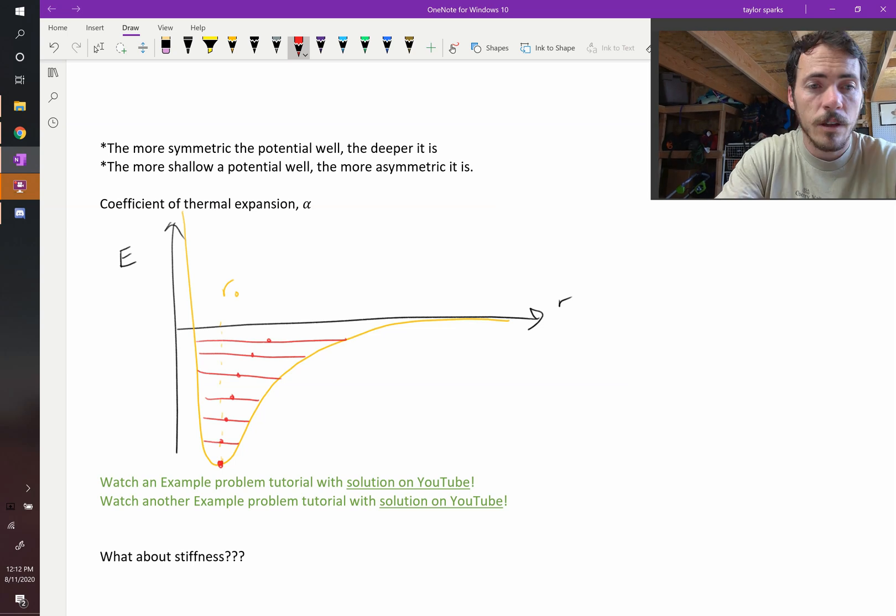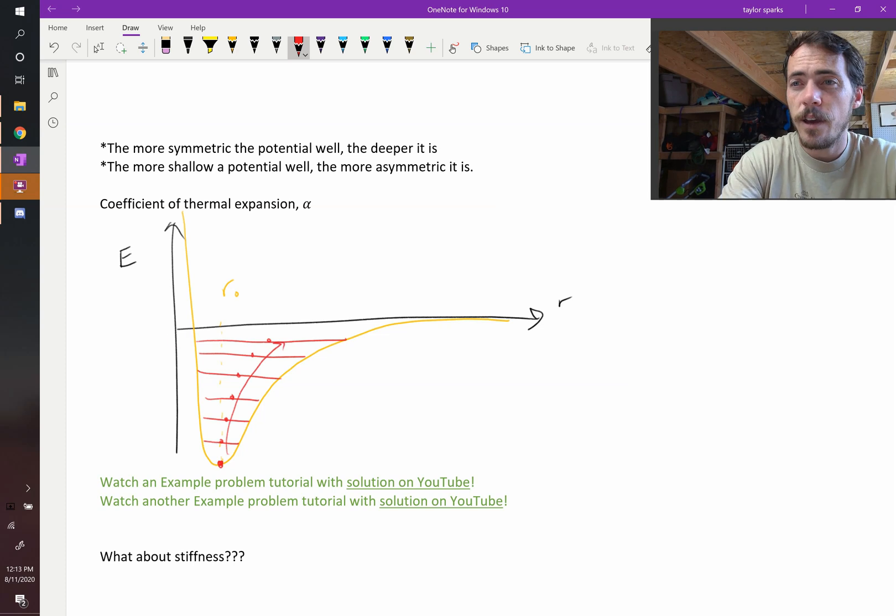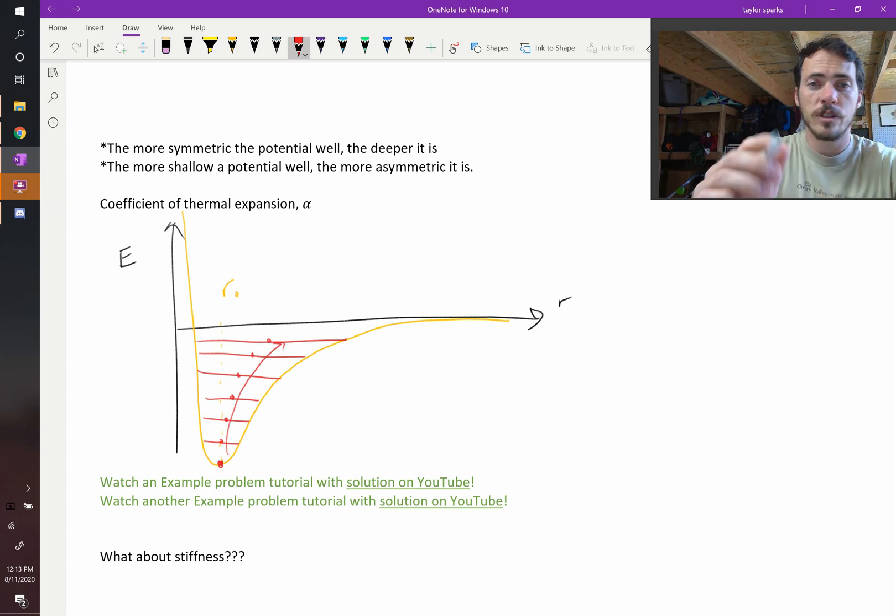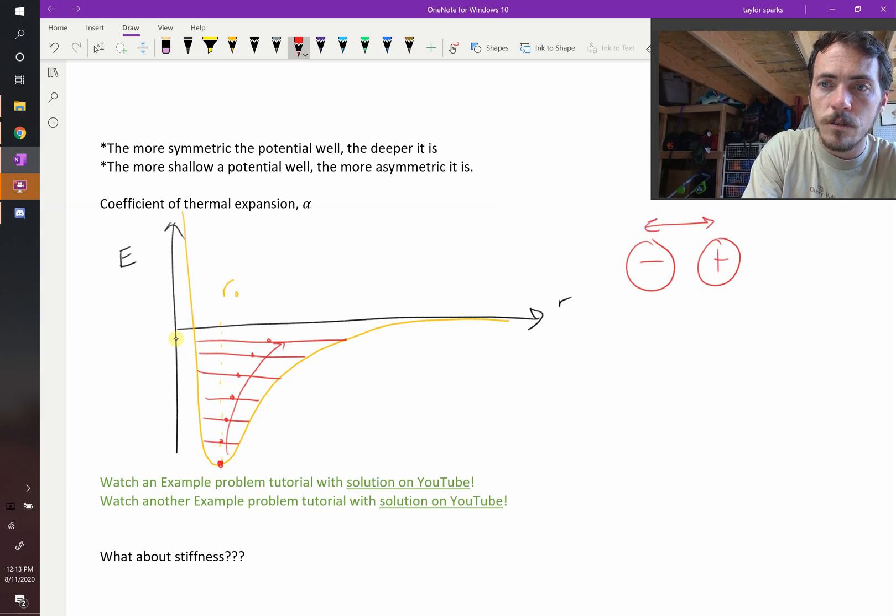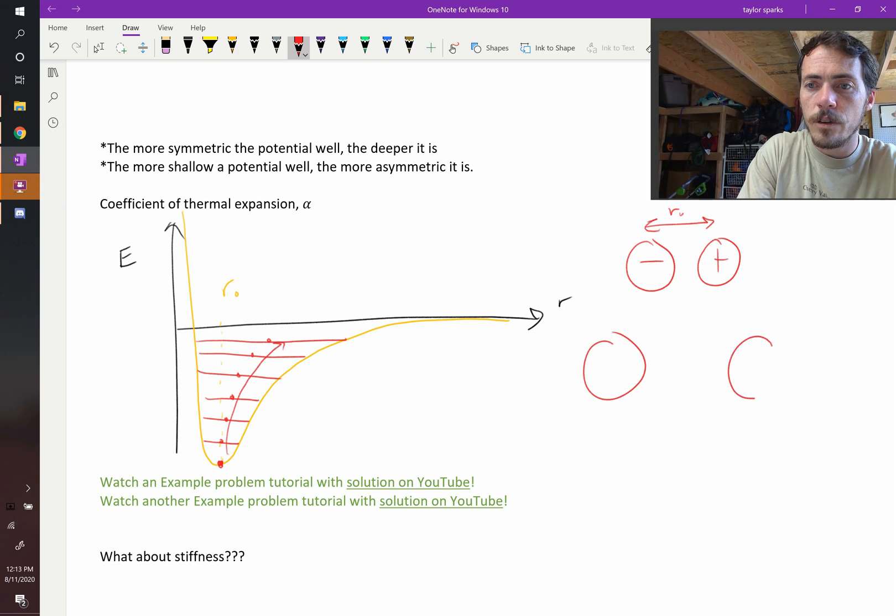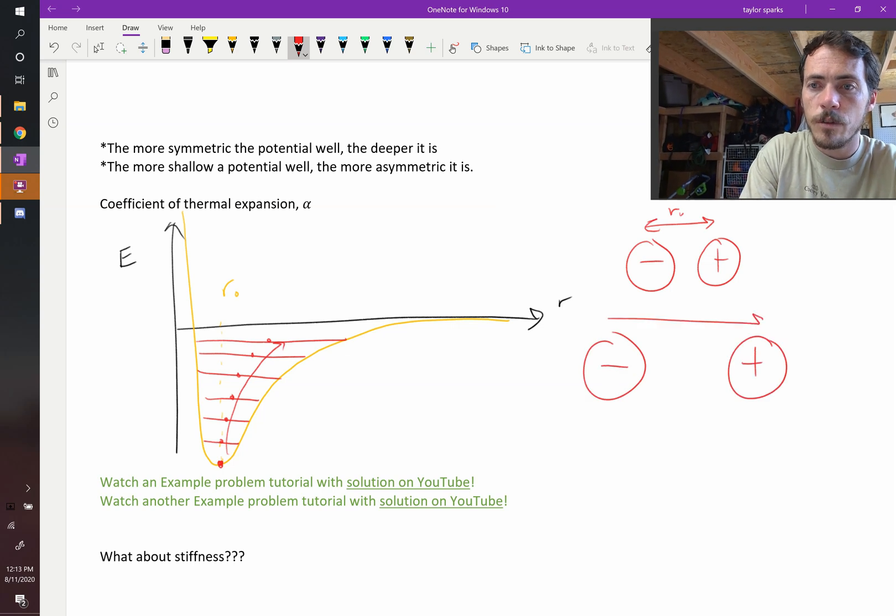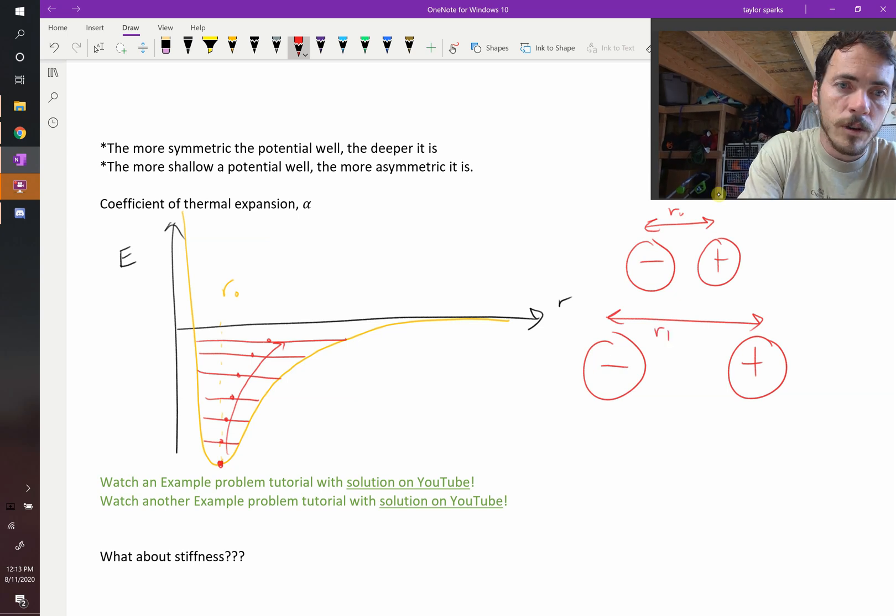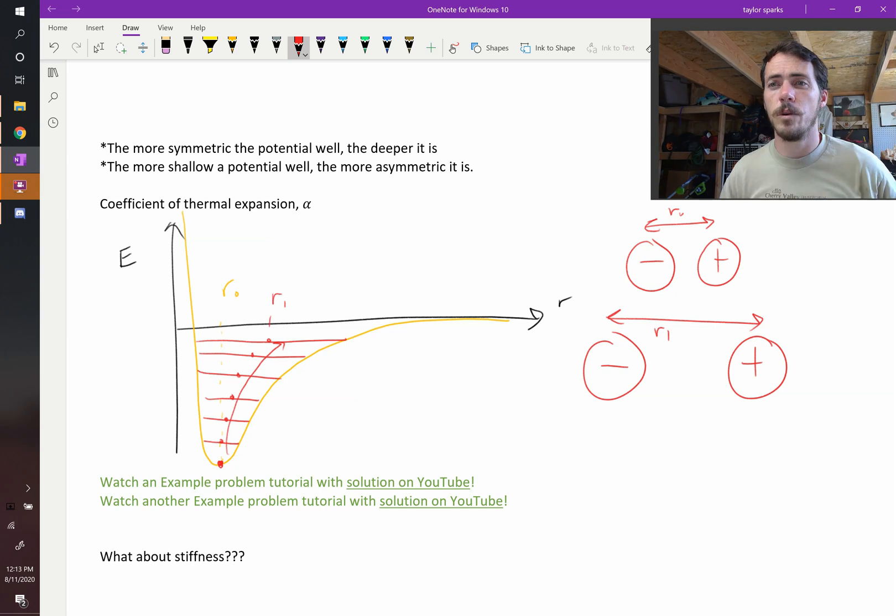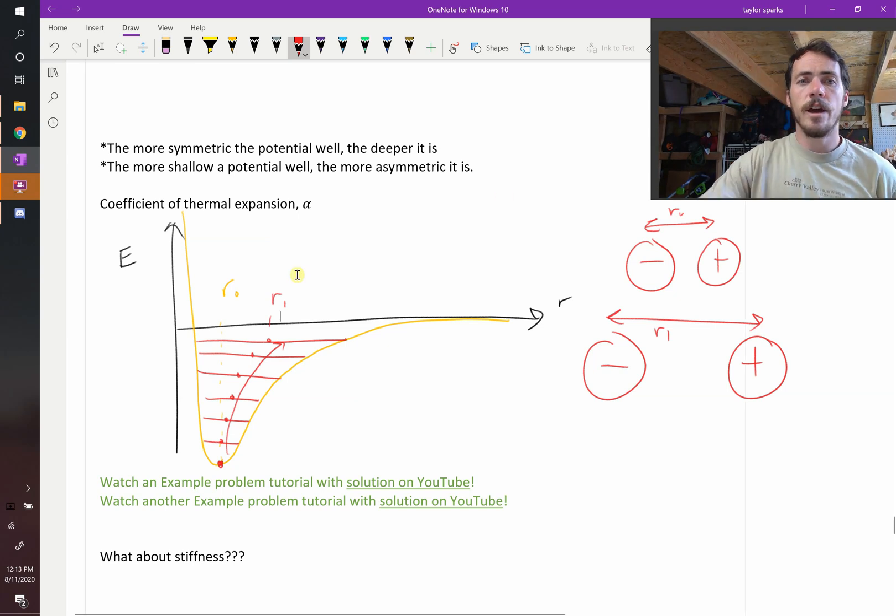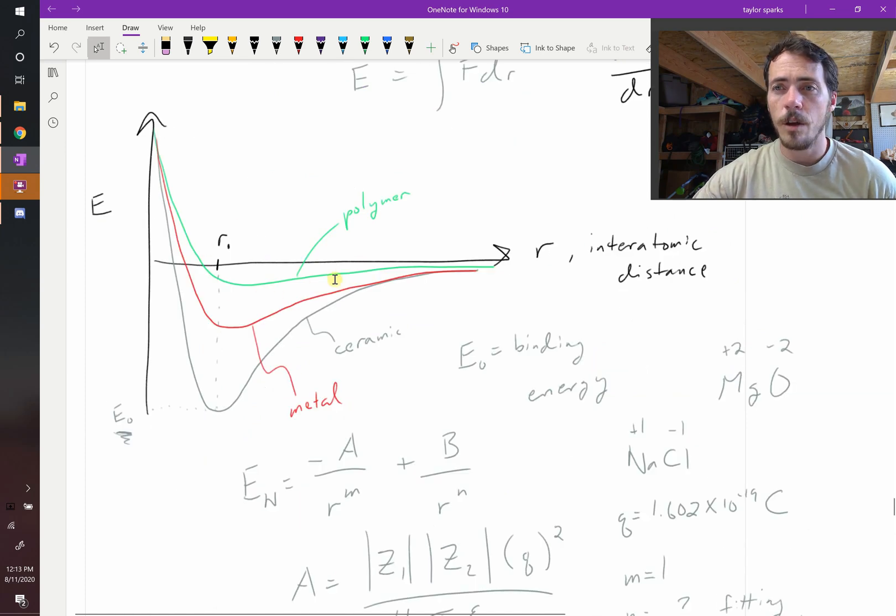What's happening to our average position as we heat it up? It's moving, right? It's actually moving with us, typically outward. It's getting bigger. The molecule's expanding. At absolute zero, your negative and your positive have like some separation distance, R-naught. But as you heat this thing up, they're literally getting more separate from one another. So this R at high temperatures, we'll call it R-one. That could be maybe right there, R-one. They're getting more and more separate from one another. So these potential energy diagrams, if you had a way to plot them and you could look at the asymmetry, you could figure out the coefficient of thermal expansion.